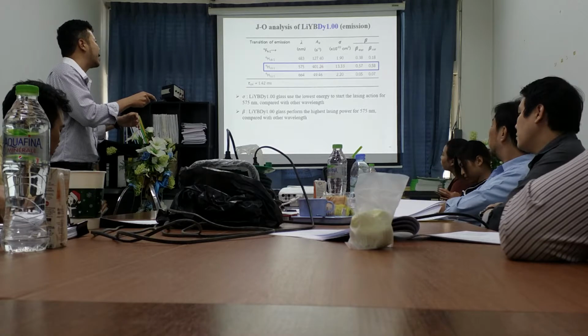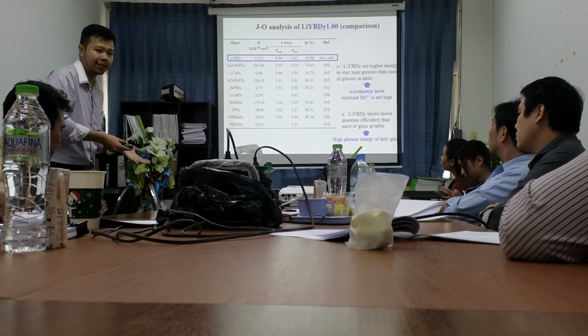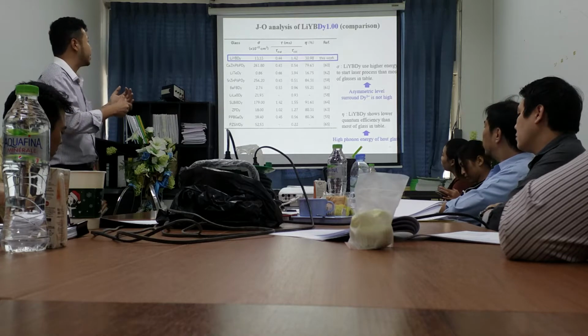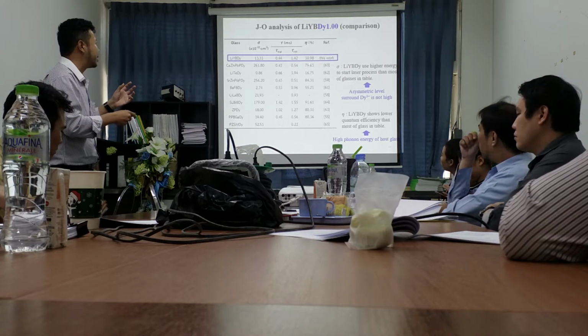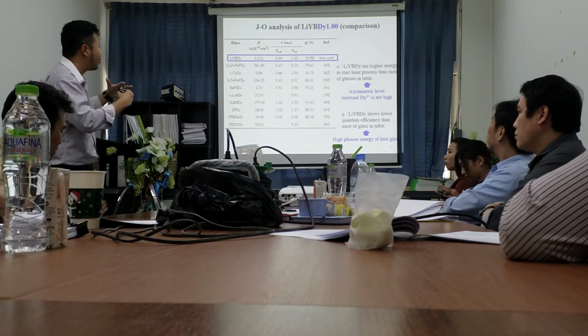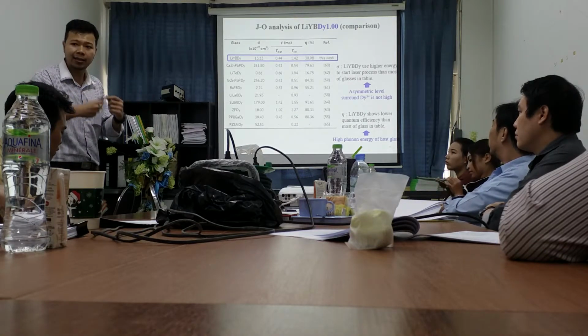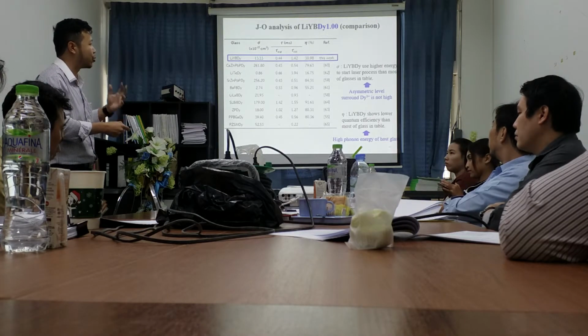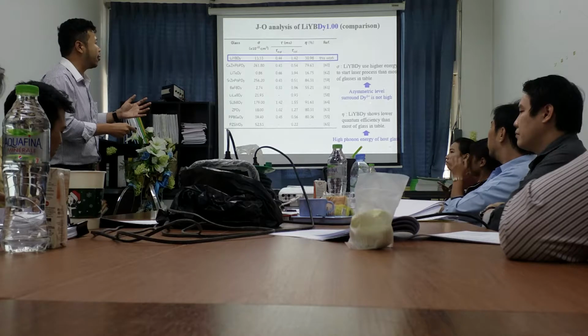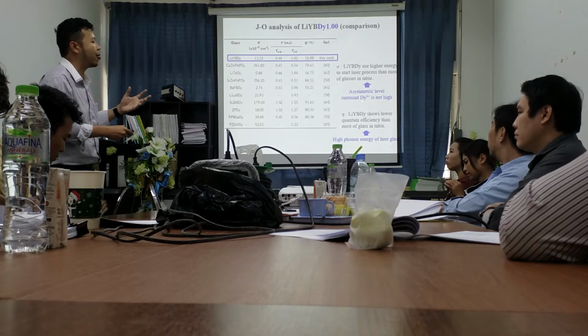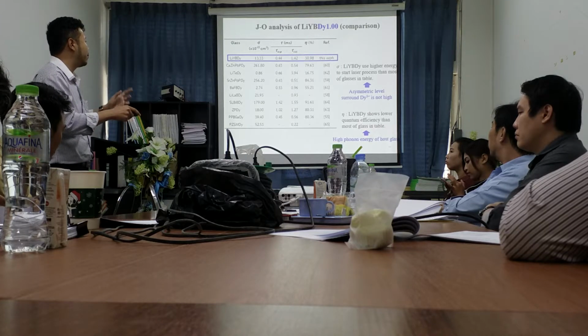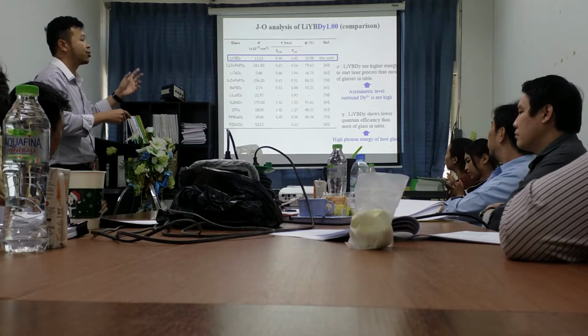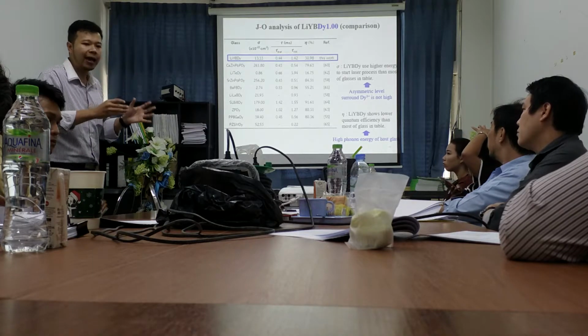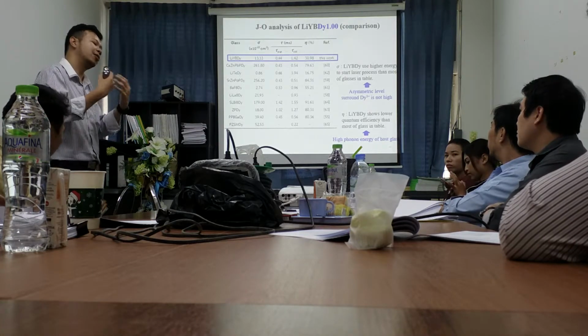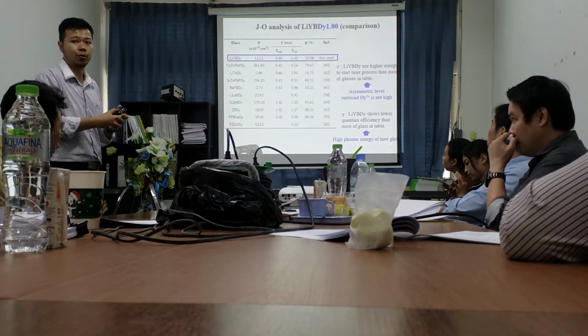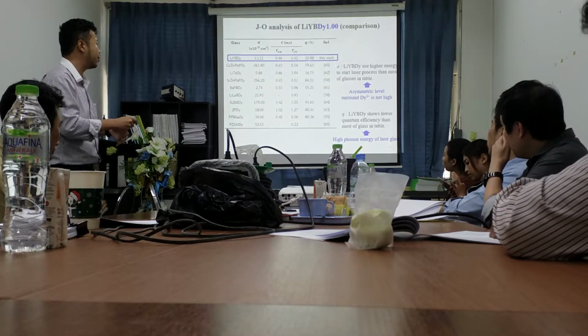However, when we compare these values with other glasses, my glass is not good because the sigma and quantum efficiency are low. That means compared with other glasses, my glass needs higher energy to start the laser process because the asymmetry level surrounding the dysprosium ion in our glass is still not high. And the quantum efficiency is also low because of the high phonon energy in my glass and because of the OH group in my glass also. This reduces the quantum efficiency.